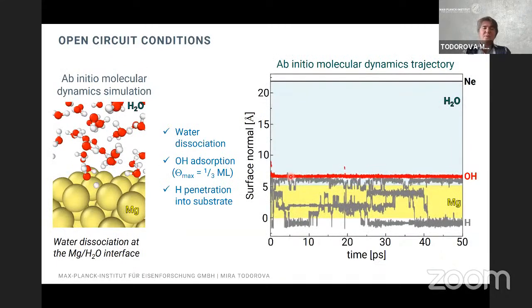And first of all, we performed calculations under open circuit conditions without applying any voltage, and let the system evolve, looking at what is really going on. And maybe you saw in the beginning that there was a water molecule. This dissociates, here can be seen again, and hydrogen then penetrates into the surface or moves along the surface. The OH stays on the surface.